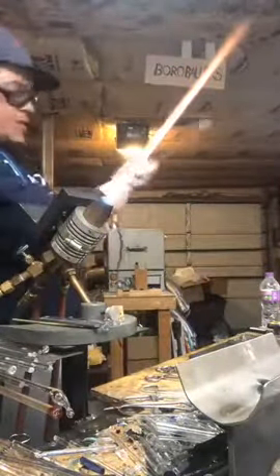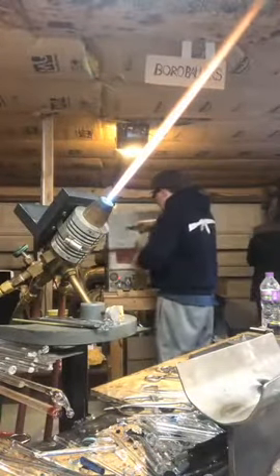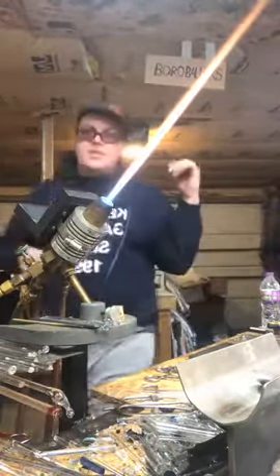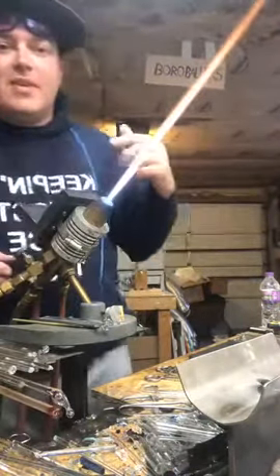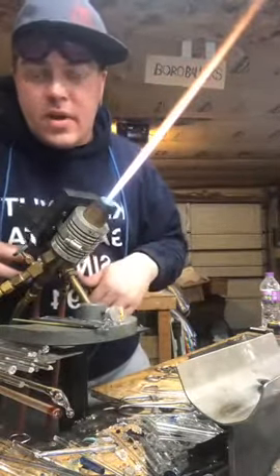Carb. This is the mushroom. Stands right up. I'm going to cut this top part off right here. We're going to put the mouthpiece there. So I just need to warm this up in the kiln for a few minutes. Kiln's sitting at about 1,000 degrees. The mouthpiece here that I got to cut was probably almost room temperature. So I needed to get it up there before I start throwing the flame, or I could just break it and just ruin everything.